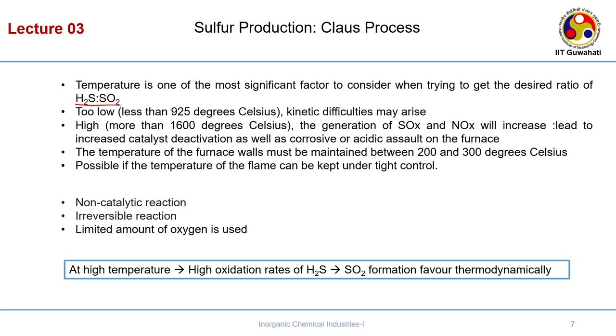In the second step, the sulphur dioxide reacts with the remaining H2S. Not all H2S is combusted — some amount remains, and that H2S reacts with sulphur dioxide to form elemental sulphur. An excess of H2S is used for maximum conversion. If the temperature is too low — less than 925°C — kinetic difficulties may arise and the rate of reaction may drop. At too high a temperature, SOx and NOx generation will lead to increased catalytic deactivation and corrosive assault on the furnace.